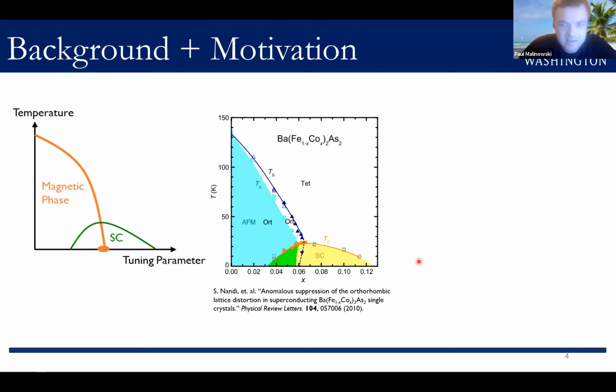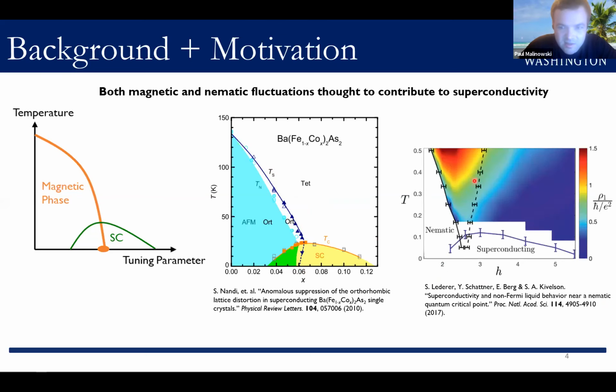Now in the iron-based superconductors, there's also the electronic nematic phase, which appears near or simultaneous with the magnetic transition, in which the electronic fluid breaks the C4 rotational symmetry of the underlying lattice. And this nematic phase is also suppressed along with the magnetic phase and ends in its own possible quantum critical point near optimal doping. Furthermore, there are theoretical considerations such as the Monte Carlo results shown here, demonstrating that in principle, nematic fluctuations can lead to an enhancement of superconducting pairing and TC near the nematic quantum critical point. So we have this overall picture in which both nematic and magnetic fluctuations are potentially contributing to the superconducting pairing.